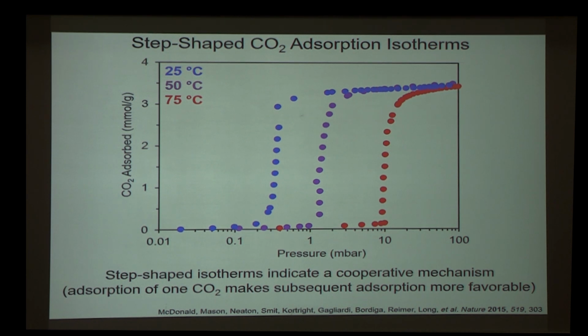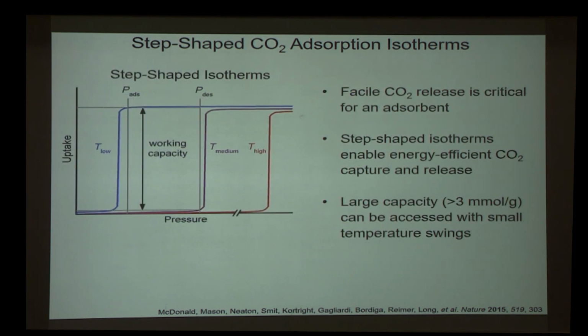What I'm showing you here is a gas adsorption isotherm, where on the y-axis, I'm showing you the amount of CO2 that has been captured, and on the x-axis, I'm showing you the pressure of CO2 to which we've exposed the sample. And you can see that at very low pressures, there's almost no CO2 capture. But you hit a critical threshold where the material abruptly transitions from empty to completely full of CO2. These unusual step-shaped isotherms are indicative of a cooperative mechanism. And what I mean by that is capture of one CO2 molecule in the material makes the capture of subsequent CO2 molecules more favorable. These step-shaped isotherms have some tremendous advantages for efficient CO2 capture in a process.